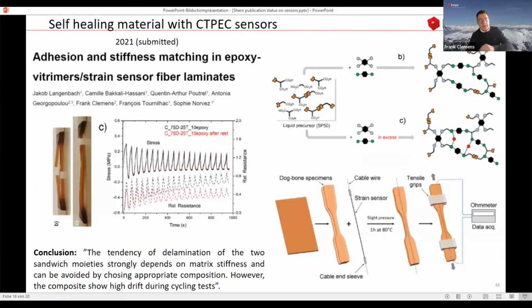Last but not least, these are some papers which are under submission at the moment. This is a paper made by the people from France. Here you can nicely see the behavior of a sensor which was integrated in an epoxy vitrimer material. When the fiber was not very well attached to the matrix, we had a delamination. However, by using some additives, it was possible to have a better adhesion between the fiber and the matrix material, and by this we could get very good sensor signals out of it.